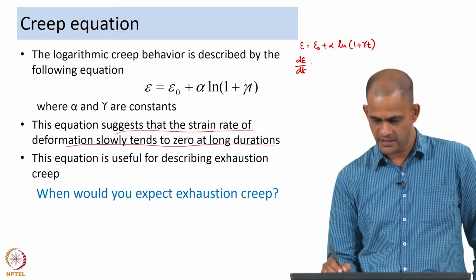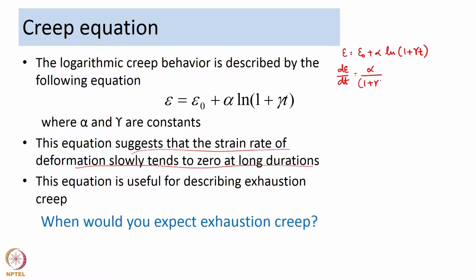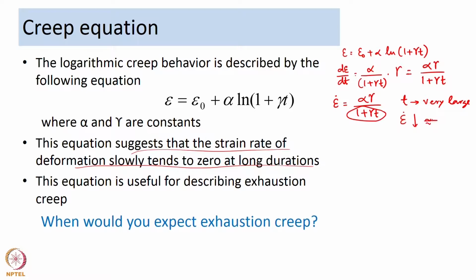So, d epsilon over dt is equal to alpha over 1 plus gamma t into gamma. So, that becomes alpha gamma by 1 plus gamma t. So, the strain rate during logarithmic creep is basically alpha gamma by 1 plus gamma t. When t tends to very high values, so say t is very large, then the denominator term becomes very large. So, epsilon dot decreases, and it tends towards 0. So, epsilon dot eventually tends to 0. If t tends to infinity, then epsilon dot tends to 0.